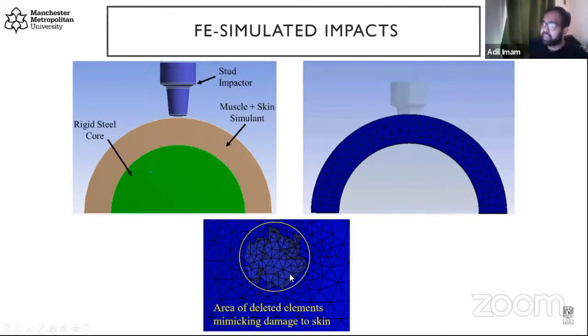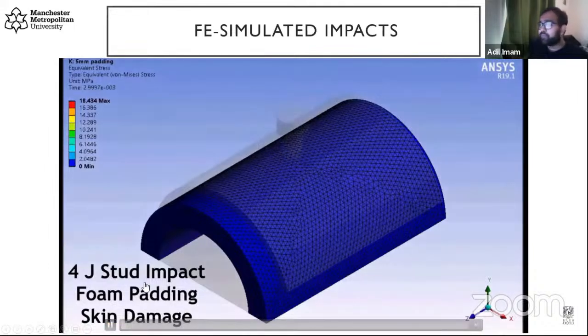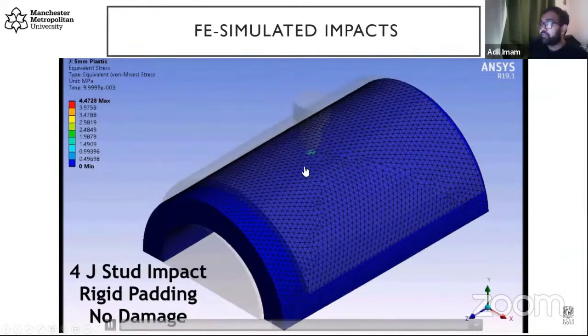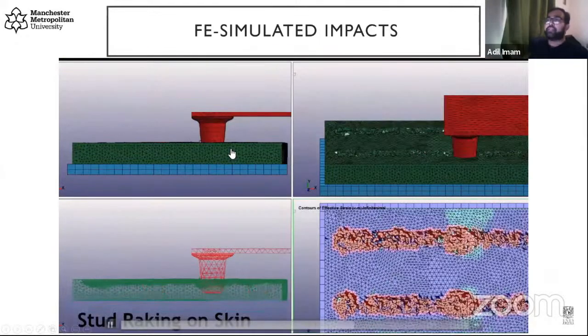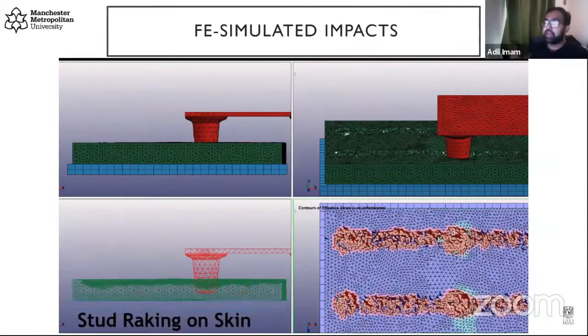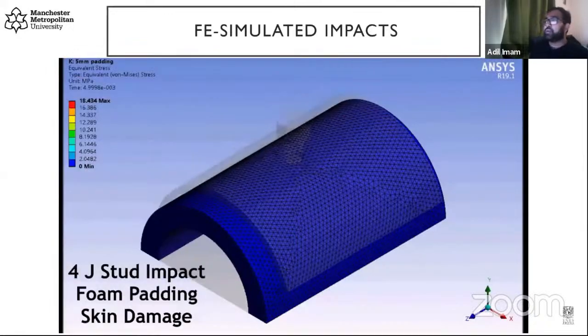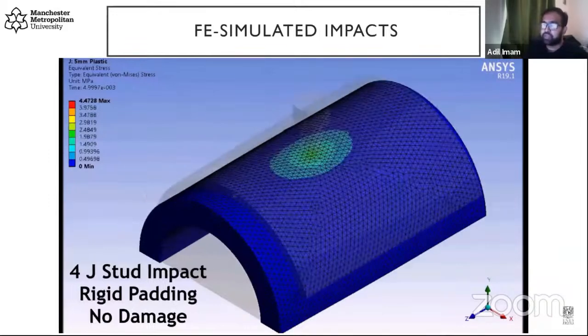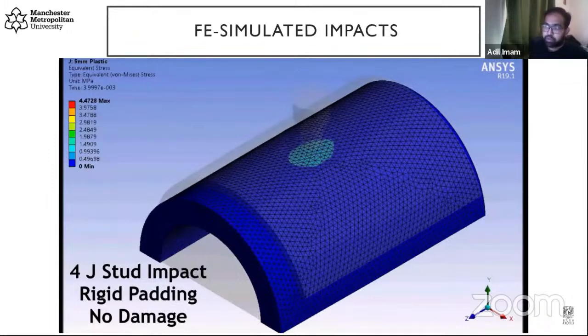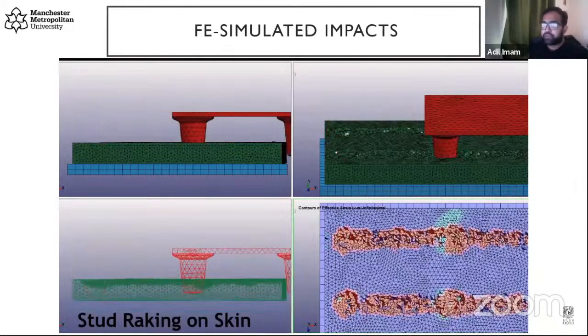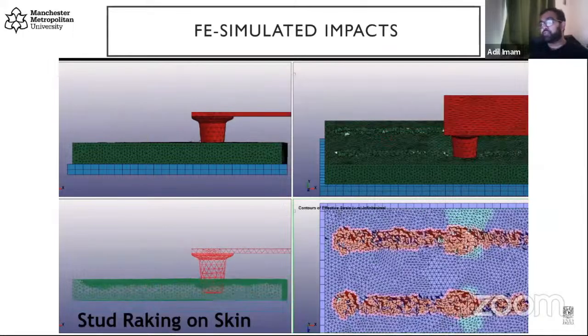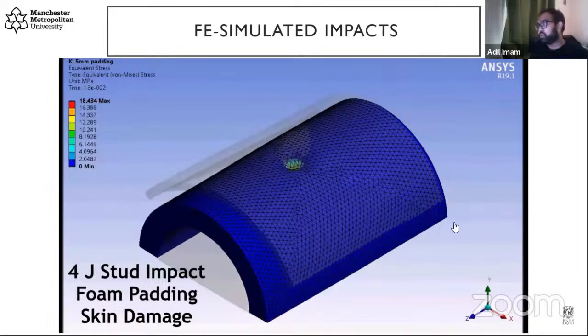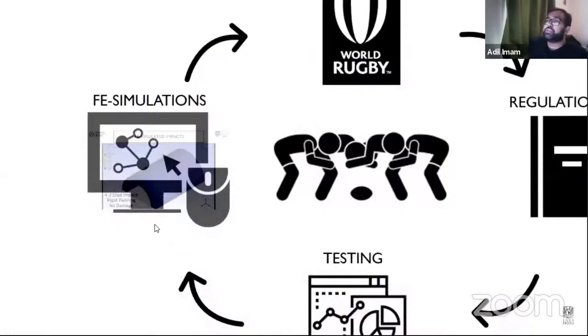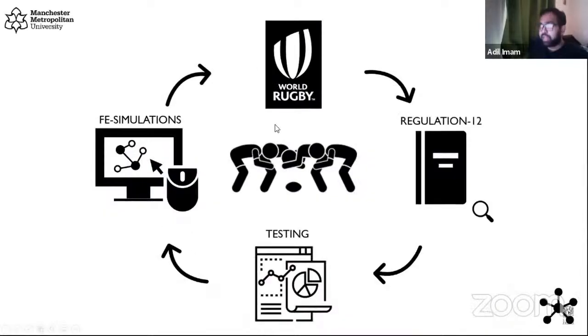So we've validated this model against our impact testing at different angles, and we've been able to run simulations. So let's say we can introduce foam paddings of different properties and see how the skin would tear if we use the soft, or if we use the stiff or a rigid padding, how the force dissipates. Not only that, we were able to simulate different impacts. So, you know, someone stamping on a player and pulling the leg back would result in a skin tear. So the ability of FE, again, is once you've validated the model, you can mimic different scenarios. And using this model, you can test out different scenarios of impact or different padding, which might be soft or rigid, and figure out, you know, if this should be allowed or this should be regulated or not. So those simulations and the data from all our testing was being fed back to World Rugby to help improve the Regulation 12.